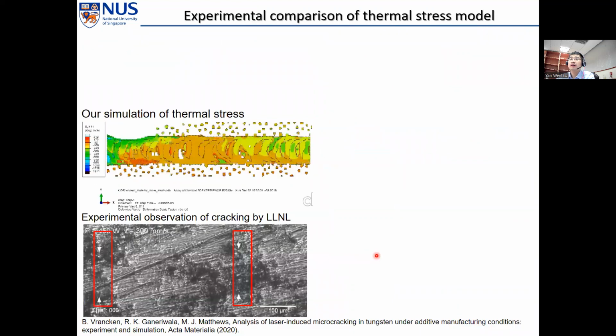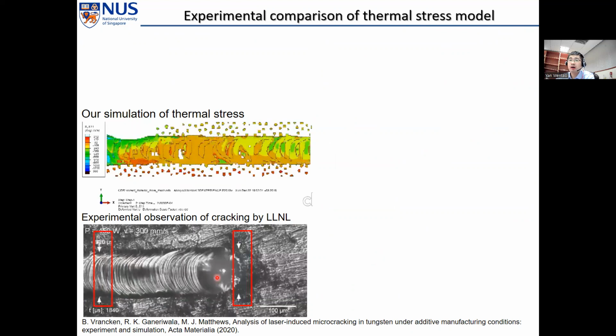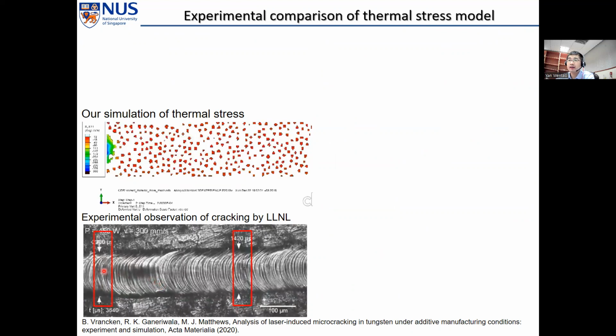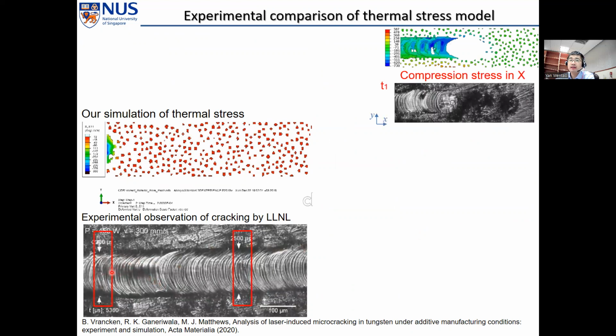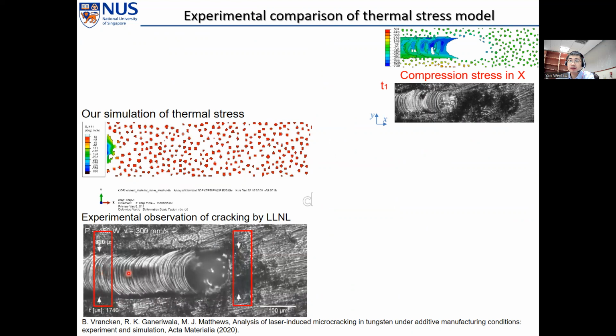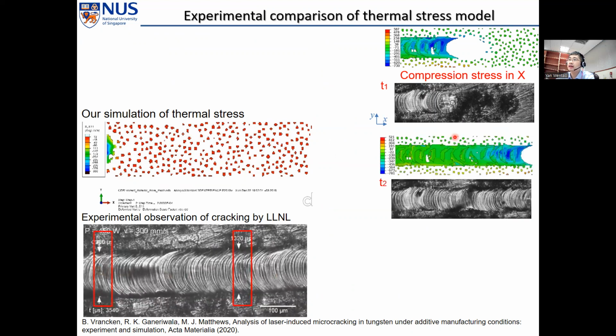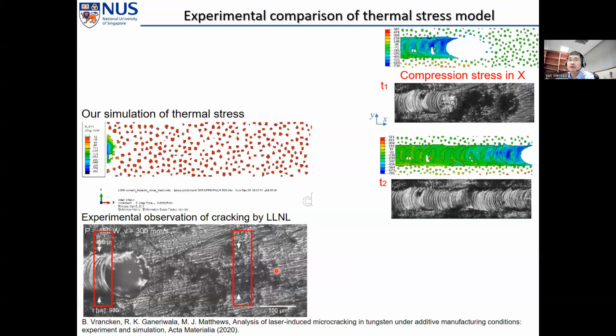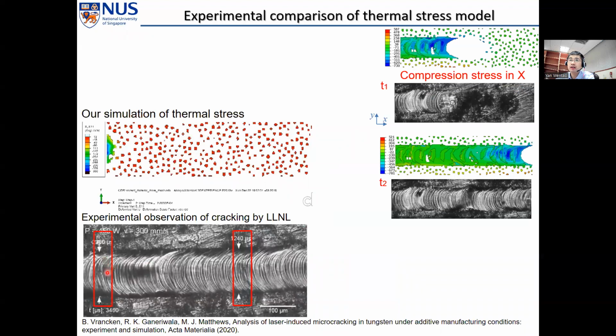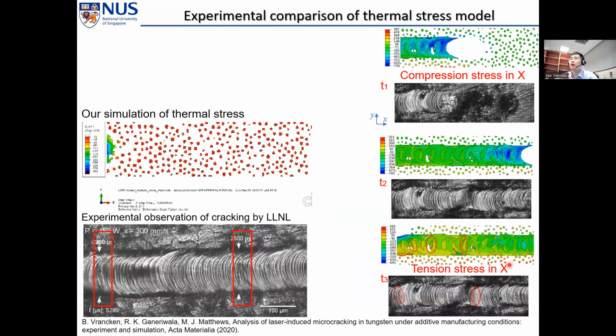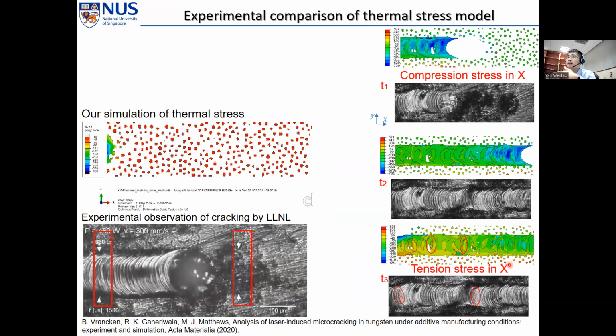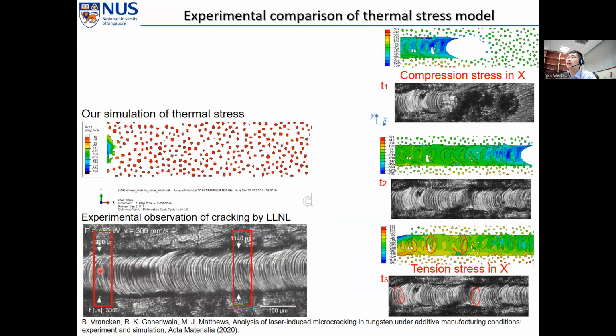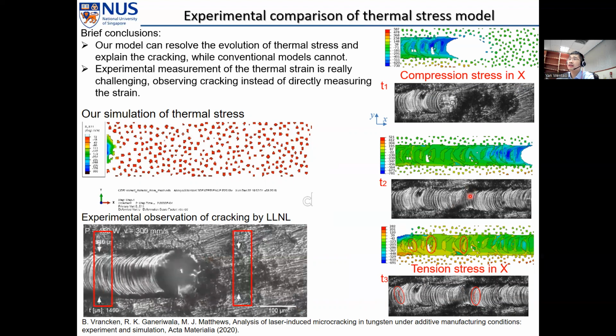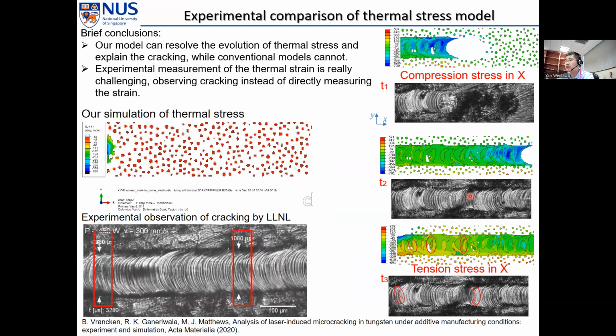So with this, we can very well explain the experimental observation of how the cracking happens. When the laser has just passed by, there's no cracking, right? Because it's compressive stress. And when it goes further, it's still compressive stress. But when it goes even further and it's further cooling down, there will be cracks here. This is because, one, the thermal stress becomes tension. Second, due to the rough surfaces, there's stress concentration, which leads to cracking. But this is just a qualitative comparison. For quantitative comparison, it's still very difficult.